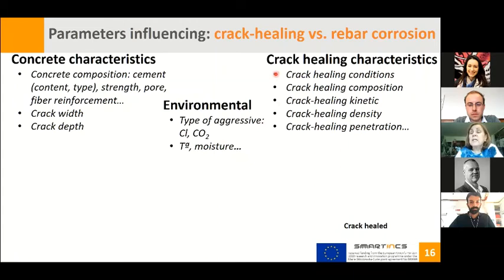And what about the crack healing characteristics? The crack healing depends on the crack healing rate and the capacity to heal, the crack healing kinetics, the crack healing density, the crack healing penetration. We have observed and presented today different cases where we can have a surface self-sealing, however not a complete self-healing inside the cracks, and not be able to protect completely the crack.